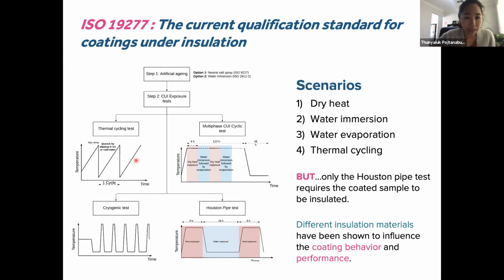We can see that the standard focuses on the thermal cycling of the coating, because we know that temperature fluctuation of the coating is a way to accelerate coating degradation. So what the standard basically simulates is the dry heat, water immersion, water evaporation, and the thermal cycling. It does not simulate the interaction or the compatibility of the coating and the insulation material.